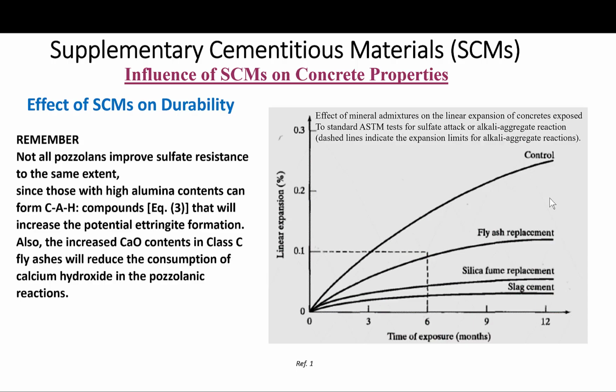This figure shows the potential linear expansion of concrete versus exposure time in months. Here is the control mix, and here is the replacement with slag, which is the best performing, followed by silica fume, and then fly ash replacement. So evidently there's an improvement in that aspect, where the linear expansion has been reduced.